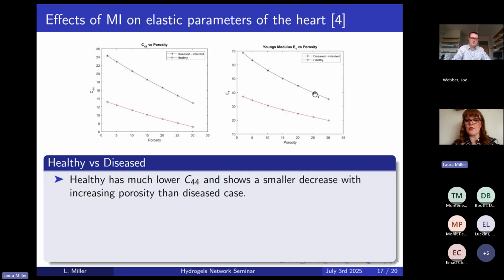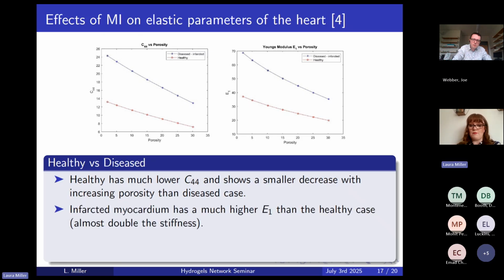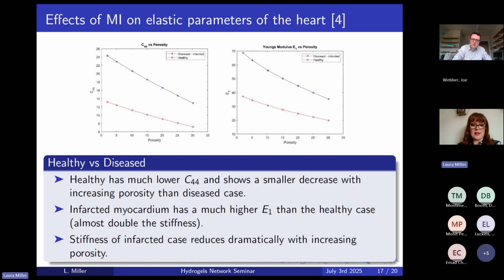And again, we did the same with the Young's modulus E1. This was the one going across the situation when the fibers are coming down like this and we're pulling the material in that direction. In fact, the infarcted myocardium has a much higher E1 than the healthy case. It's almost double the stiffness. And indeed, the stiffness of the infarcted case does reduce dramatically with increasing porosity. So that goes towards the idea that increased reperfusion of the heart muscle post myocardial infarction is very good at softening the heart and increasing its compliance. But we do need to think about which levels then become detrimental to the efficiency of the heart.